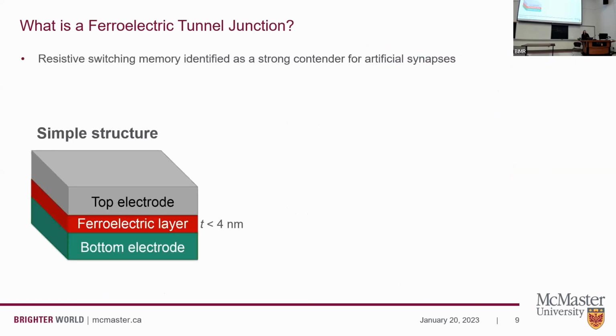So, what is a ferroelectric tunnel junction? As I said, this is a resistive switching memory with two stable resistance states that can be exploited for artificial synapses. The device structure is very simple and can be seen on this figure, where we have a ferroelectric layer that is sandwiched between two metallic electrodes. The only characteristic of the ferroelectric layer is that its thickness is not above 4 nanometers. So it's a very, very thin, or also called ultra-thin film.